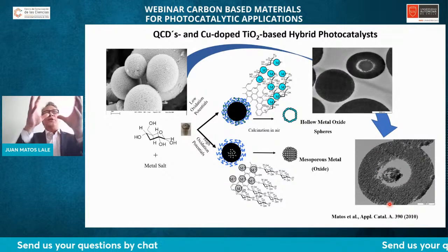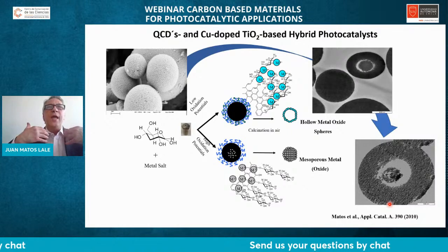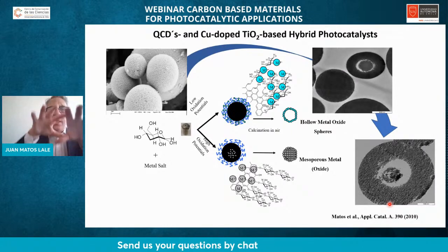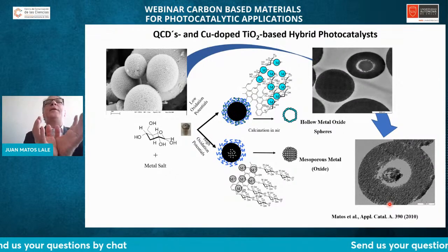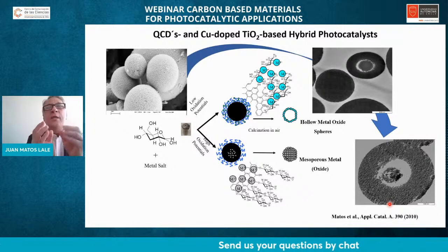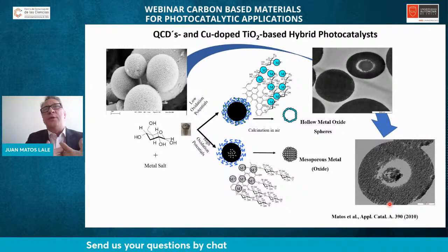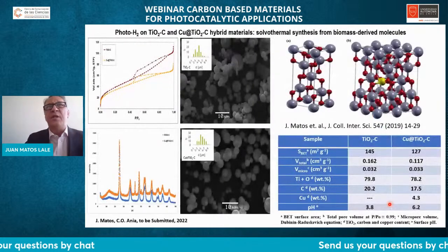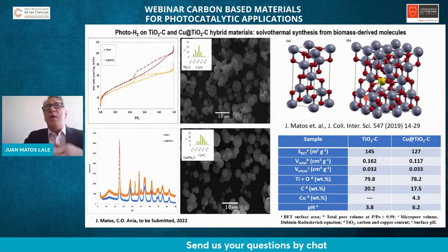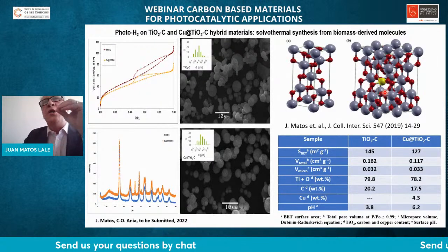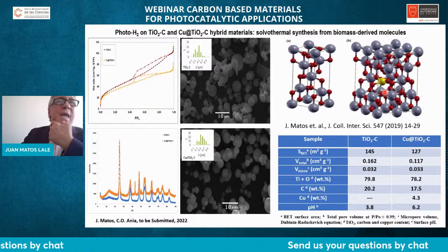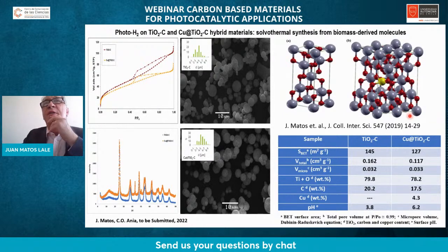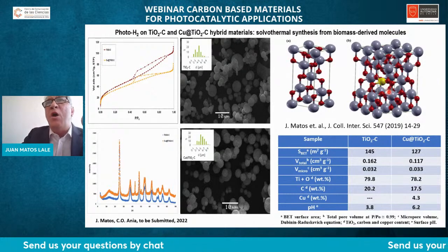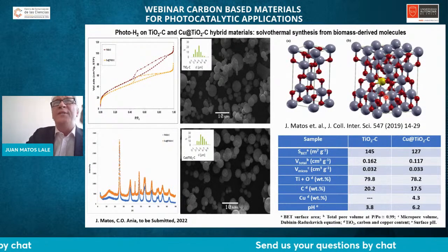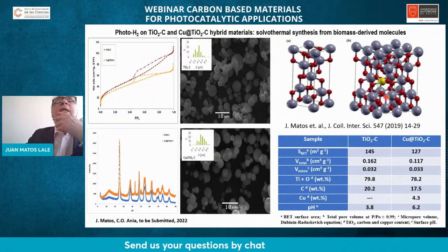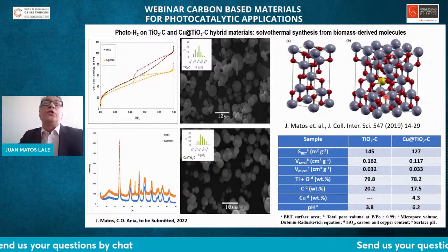In other words, if you have an ordered mesoporous material able to get the light or irradiation through the solid to the inner space, once it arrives at the inner space, there is no scattering. All the light is confined within the sphere. That is why we are talking about a harvesting efficiency factor. And we published it 12 years ago. And more recently, 3 years ago, we demonstrated the possibility to reduce the energy band gap to around 2.8 electron volts for titanium dioxide based photocatalyst with only 1% of carbon doping. And the carbon in this supercell was able to control the possibility of being excited under solar irradiation.